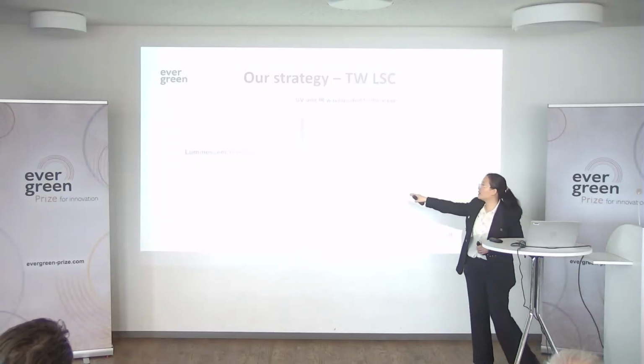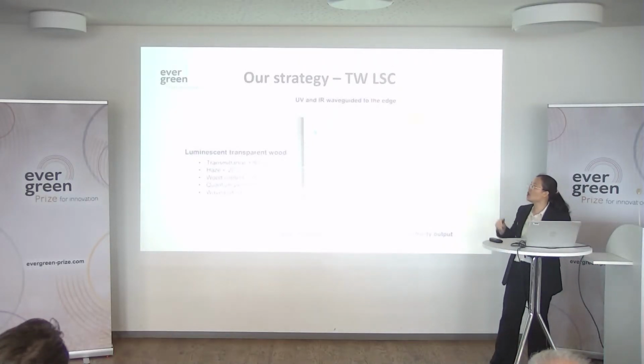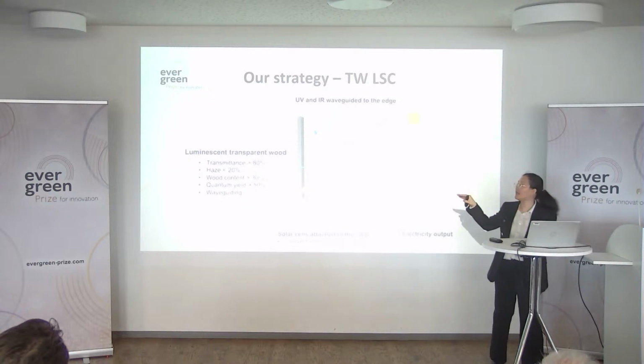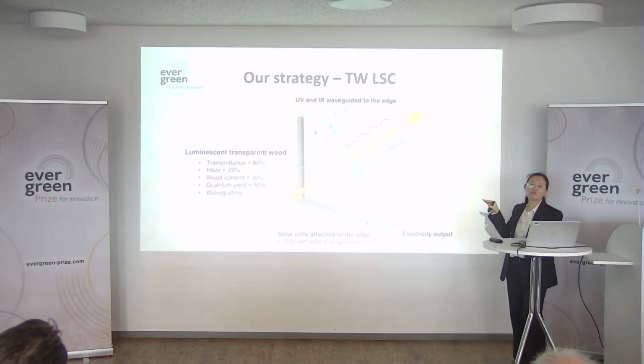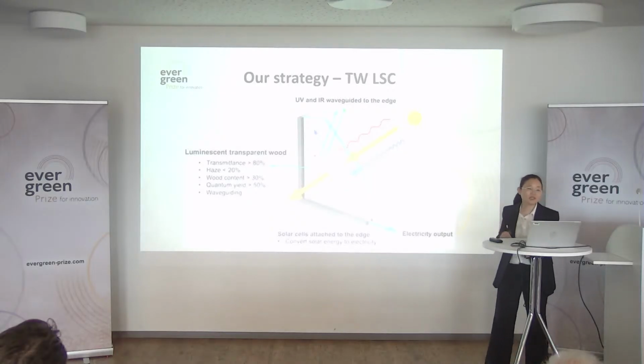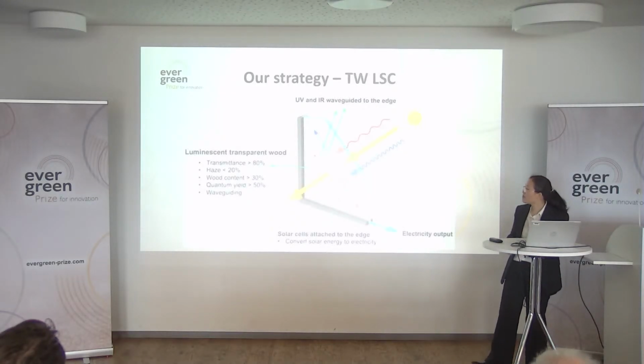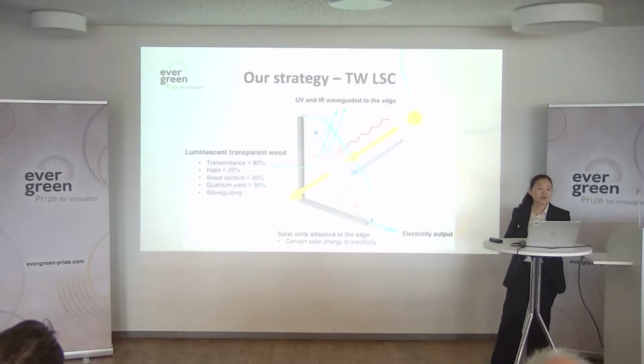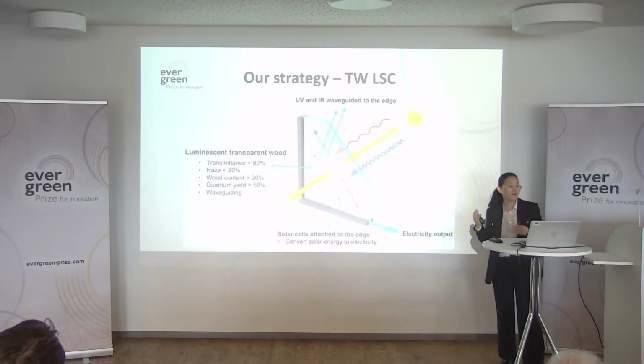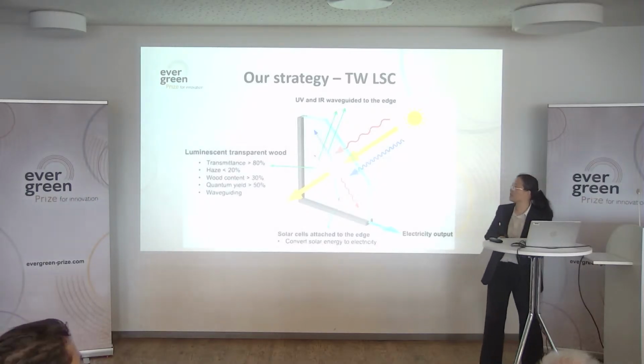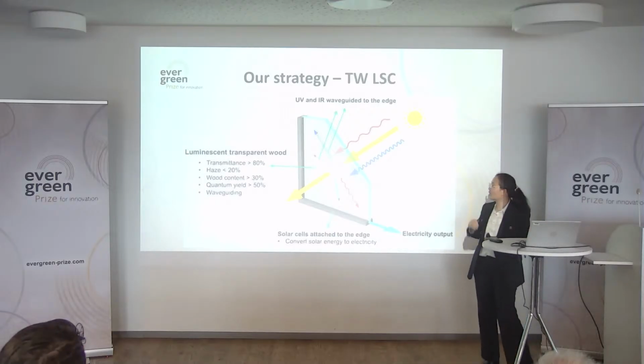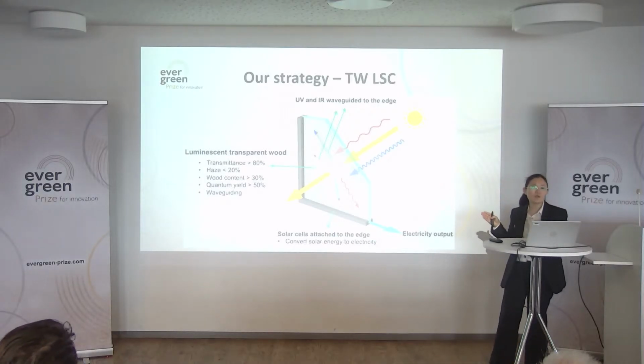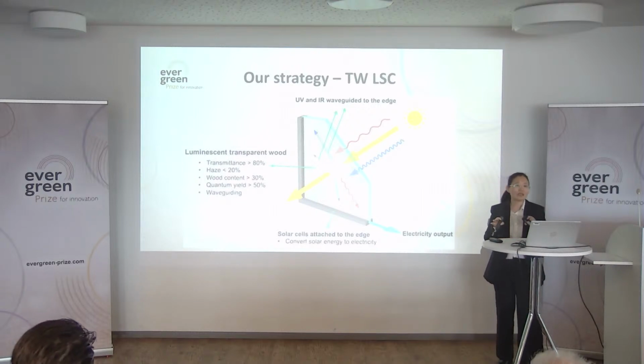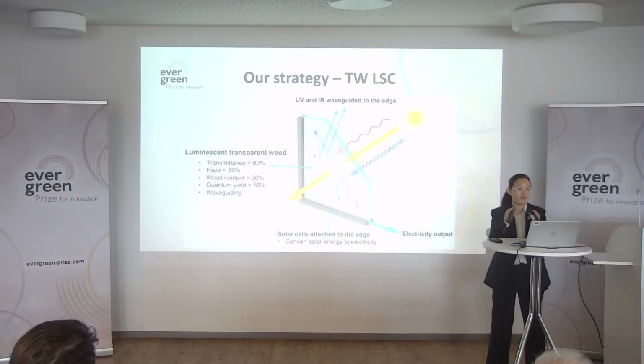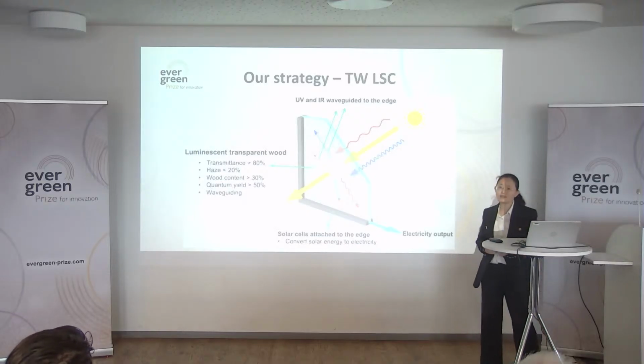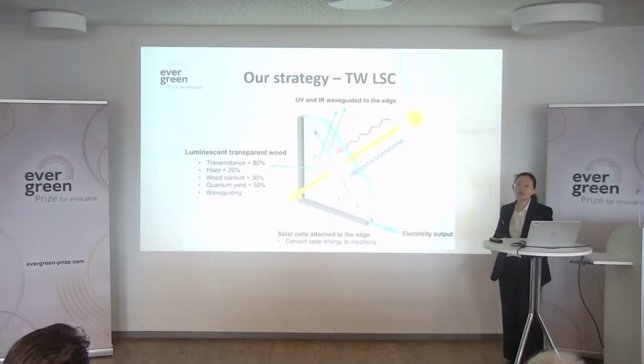Our goal here is to get luminescent transparent wood with transmittance over 80% and haze less than 20%, wood content over 30%, and the quantum yield of this luminescent transparent wood over 50%. Why do we want to have a high transmittance? Because we want to get this aesthetic view of the window. So we want to have higher transmittance and also want to get more light. And then the haze is lower because if you have high haze, you will have a high light loss during the propagation from the face to the edge. So we need to have low haze for this device.